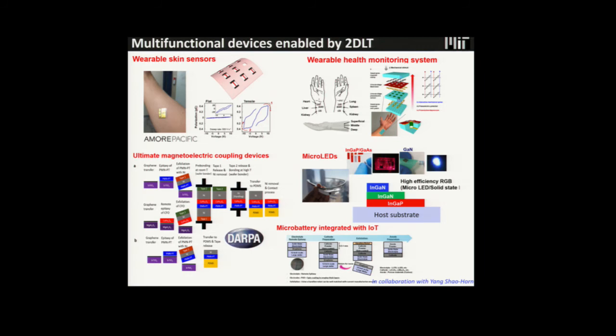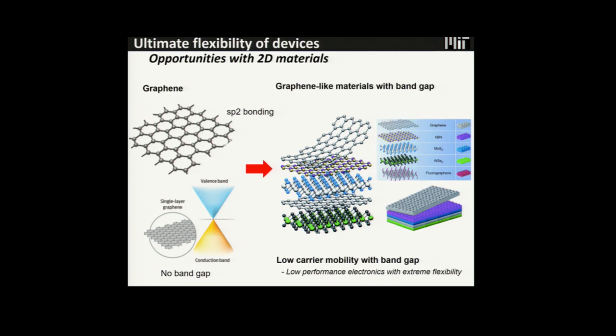We are able to peel off single crystalline piezoelectric material and single crystalline magnetostrictive material, then put them on. And we also apply this to the micro battery because we can have a single crystalline electrolyte. Also, we are developing a way to grow single crystalline silicon carbide thin membrane to be used for quantum electronics. And we cannot miss the chance to use 2D material in this activity because 2D material is extremely flexible. Our goal is to mix and match thin 3D material and thin 2D material all together. The device design can be done with a lot of freedom by doing so.